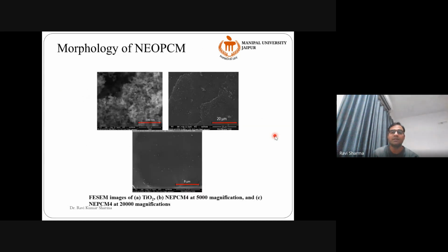So what happens once we add the nanoparticles? If you look at these FESEM images, this is the image of nanoparticles, and these two are images of PCM with nanoparticles at different magnifications. You can see these white spots are the nanoparticles which have been dispersed uniformly into the material.